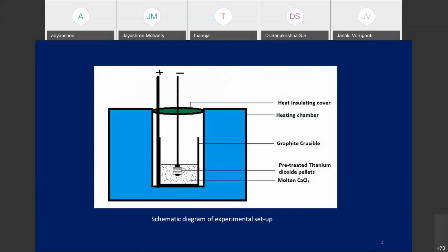And in that graphite crucible, you have to place the fused calcium chloride, or anhydrous calcium chloride. This anhydrous calcium chloride doesn't contain any moisture. For moisture removal also, you have to carry out some procedures, like heating the calcium chloride for a certain time period at a very low temperature, 100 to 200 degrees centigrade.